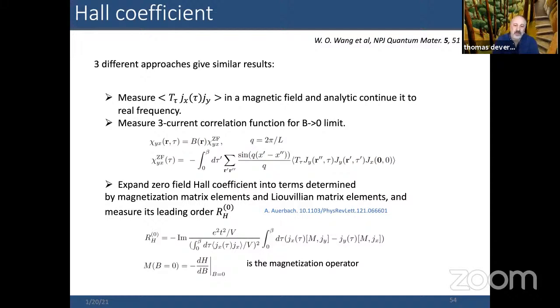The other is the zero field limit, which means evaluating a three current correlation function and plotting that as a function of temperature. And the third one is to use a method that Assa Auerbach has discussed that we've checked out, which is doing an expansion in terms of these Liouvillian matrix elements and measuring it to leading order, which involves moments of the magnetization with the current. So we've done all three of these and can show that all three give similar results as B, the magnetic field, goes to zero.